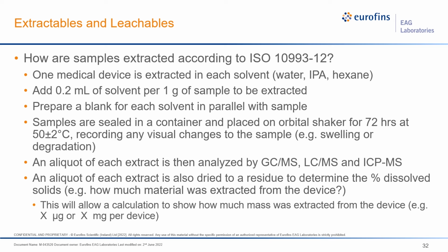So how are these samples actually extracted? For this, we took one whole medical device, which will include both the layers, and we put it in the appropriate solvents, and we used a fixed ratio of 0.2 mL of solvent per 1 gram of sample. And as you saw in the previous slide, we'll be preparing a method blank alongside the actual sample extractions. This will allow us to account for any signals that we detect that are due to the solvent, materials, or containers that are involved in the extraction process.